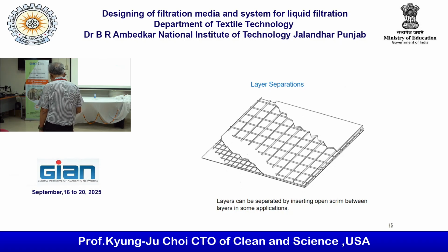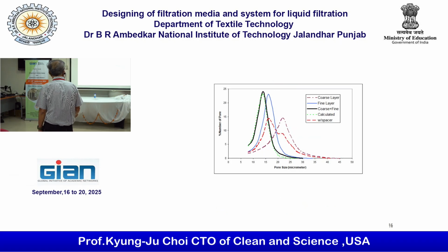Here, this is an interesting one. That is the coarse layer, looks like this. The blue one is the fine layer. If you combine both of them without any space, then you have this one. So, in fact, the mean flow pore size is going to be a lot smaller.